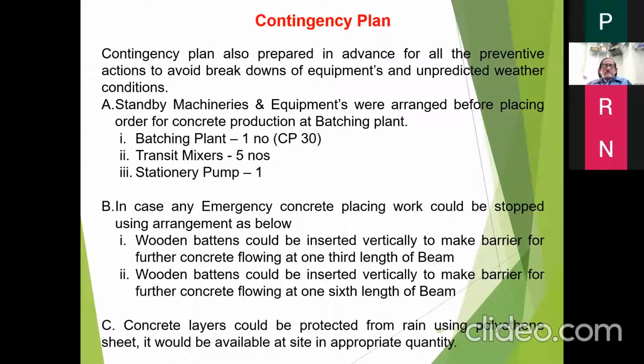In case of any emergency, the concrete pumping work could be stopped using an arrangement. Wooden battens could be inserted vertically to make a barrier for further concrete flow at 1/3 length of the beam, and also at 1/6 length of the beam. These positions were taken from the structural engineer, in case we had to stop the concrete for any unforeseen things, for which we were prepared.